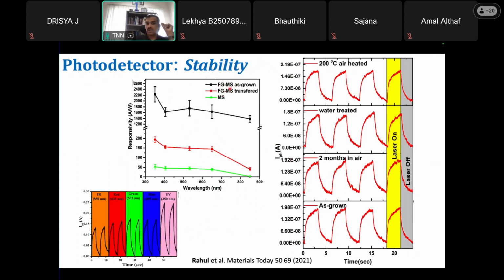I used a material called fluorographene and MS, where MS is a single layer of molybdenum disulfide. Since it cannot be used alone because of stability issues, although alone it is a nice photodetector, we use the FG in combination with the MS. In this first red case, I grew a MoS2, and then transferred another fluorographene layer on top of it by a transfer method. But in this black one, what I did is that we grew the FG in situ on MoS2. So in principle, red and black are the same material, but the two different ways the transfer happens, right?